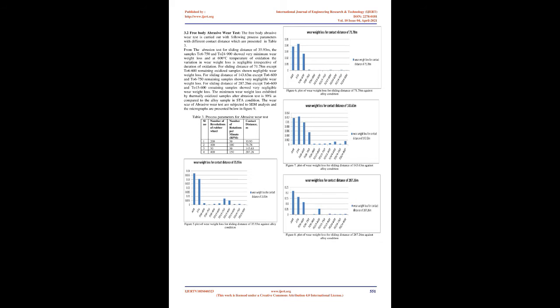The samples are cleaned thoroughly and washed in cleaning agent and weighed to 4 decimal accuracy in an electronic weighing scale before and after each test. The abrasive used for the test is rounded quartz sand grains of AFS 50/70 grade. The results obtained are presented in Table 4. Further, the abraded surfaces of samples subjected to abrasive test are examined in scanning electron microscope to understand the wear pattern of the alloy, which is presented in Figure 9.